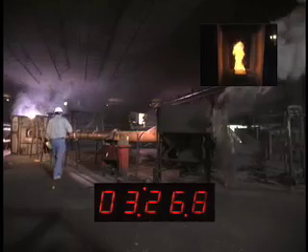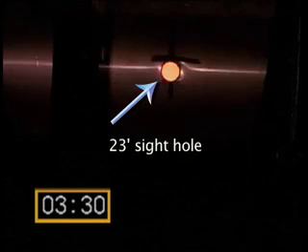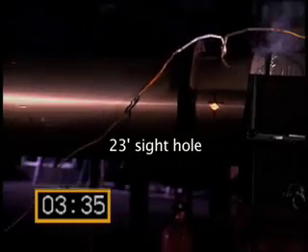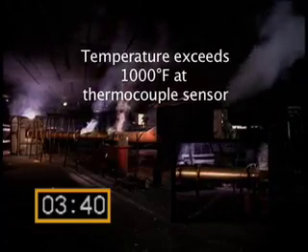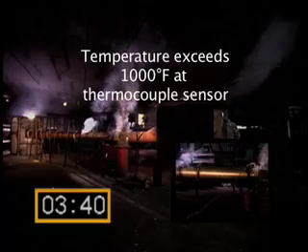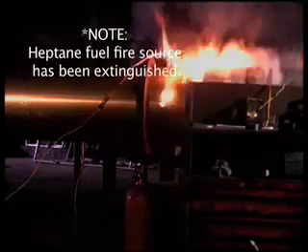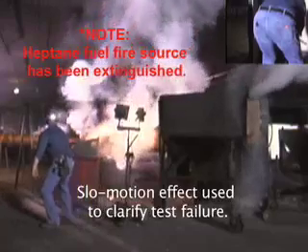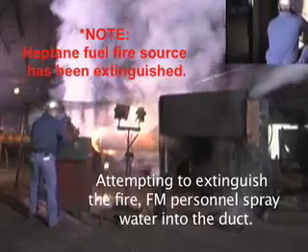This test is designed to last 15 minutes. However, the duct in this test failed at 3 minutes and 40 seconds, with flame seen inside the duct at the viewport 23 feet from the fire source. The temperature at the 23-foot thermocouple exceeded 1000 degrees. When the test is terminated and the heptane fuel fire source had been extinguished, flame can still be seen inside the duct. The ETFE coating at this point had become its own fuel source and is supporting combustion.